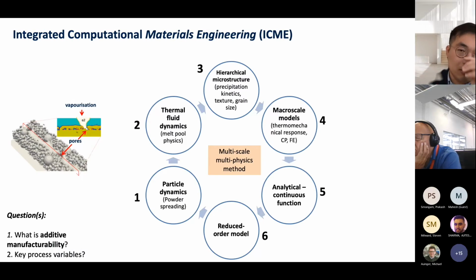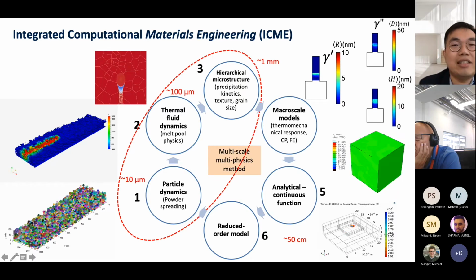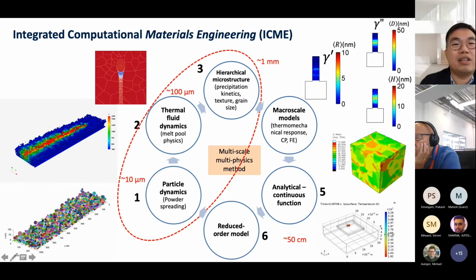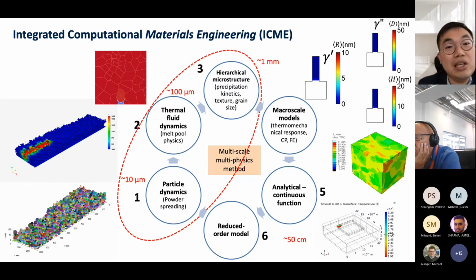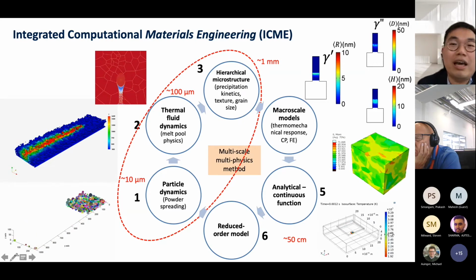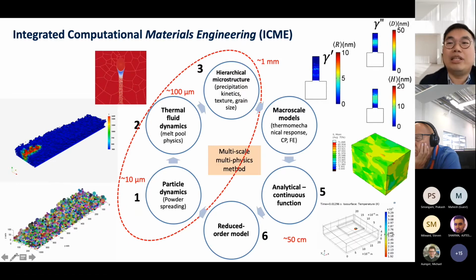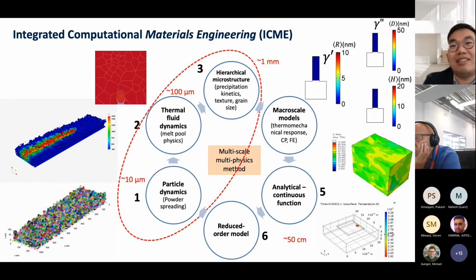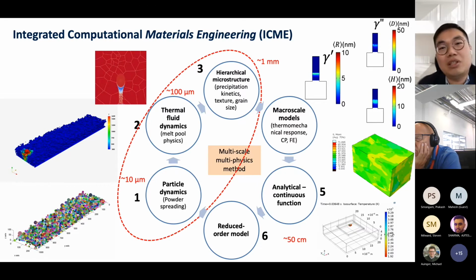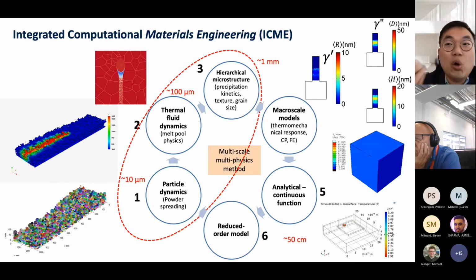So the way we have been doing in the past years is using the integrated computational materials engineering approach in order to answer what the manufacturability is from this process, once we understand the interaction of the laser heat source, and what the important key process variables are that control everything. So from the particle dynamics at the tens of micrometer length scale to the thermofluid dynamics in the melt pool physics, how it's actually printed, what the solidification sequence is that we want to know from the solidification model, and hierarchical microstructure simulation, precipitation kinetic simulation, for example, to understand the scatter in the process. It's not just everything deterministic now. We have to control the noise from